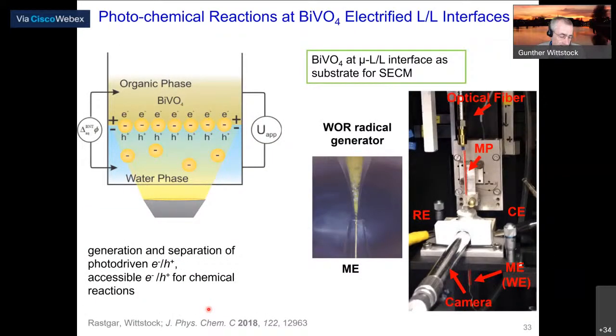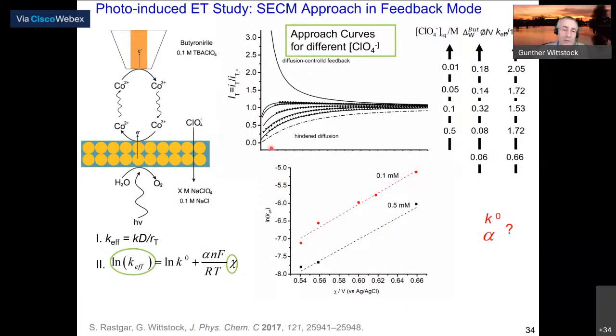Okay, this looks like this. And as a system, the interface is actually reduced to a very small size in a capillary in order to align it collinearly with a microelectrode with the help of a microscope. And then all the experiments which we did before at solid electrodes, we can now do at this liquid-liquid interface. So here we see approach curves which were fitted, which have different kinetics for the regeneration of the mediator, which takes up a photo-generated electron.